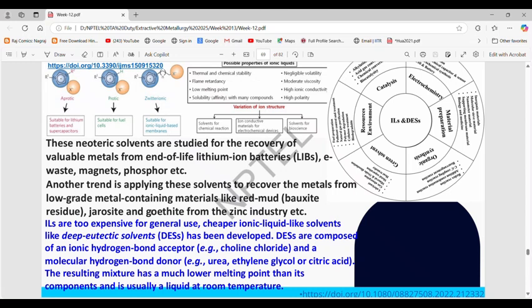So ionic liquids are too expensive for general use. Cheaper solvents like deep eutectic solvents have been developed. Deep eutectic solvents are composed of an ionic hydrogen bond acceptor, which is generally choline chloride, and a molecular hydrogen bond donor that can be urea, ethylene glycol, or citric acid, or formic acid, or oxalic acid, depending on the requirement. The resulting mixture has a much lower melting point than its components and is usually a liquid at room temperature. Basically, if you talk about choline chloride and urea or ethylene glycol or citric acid, at room temperature these are basically powder.